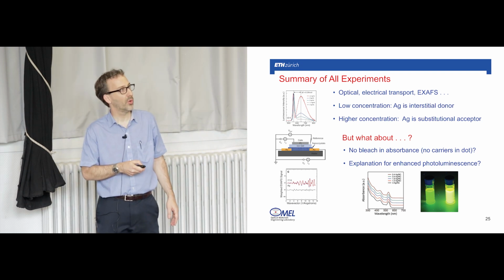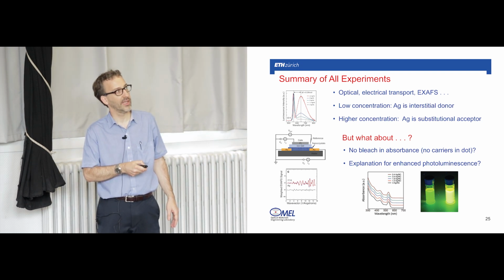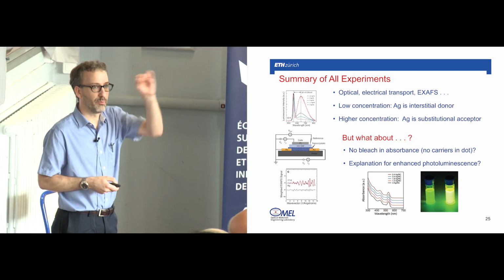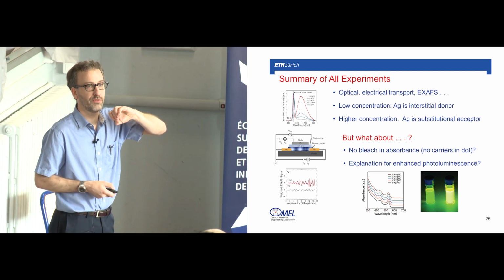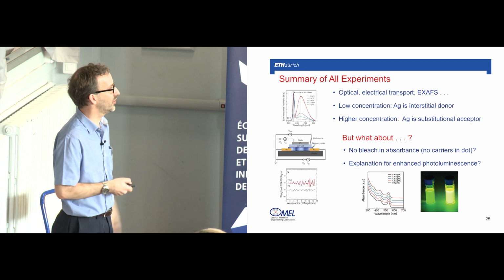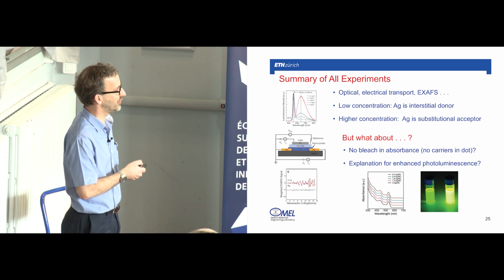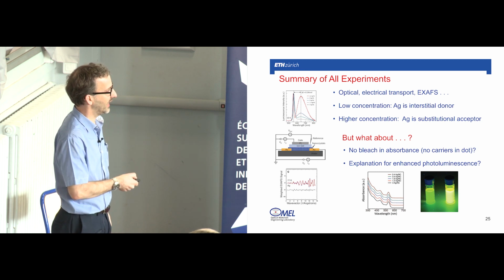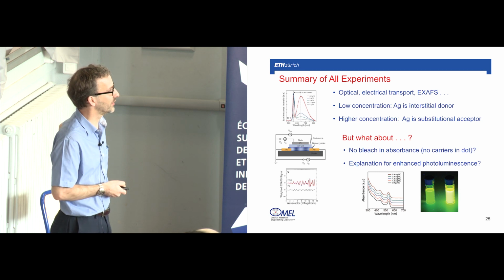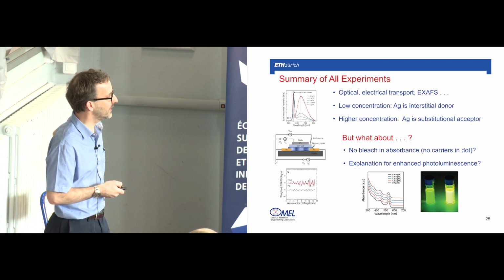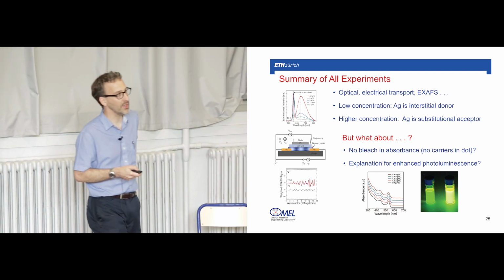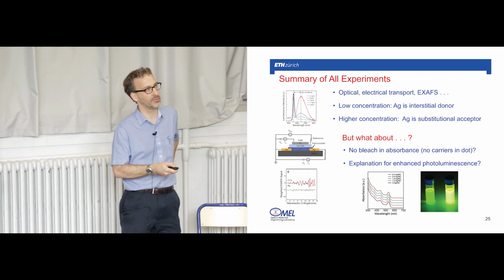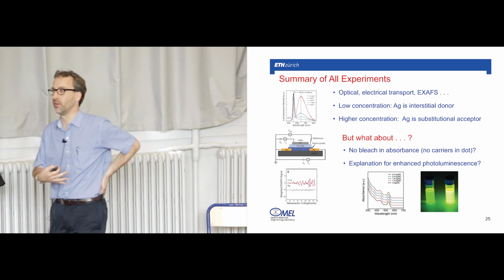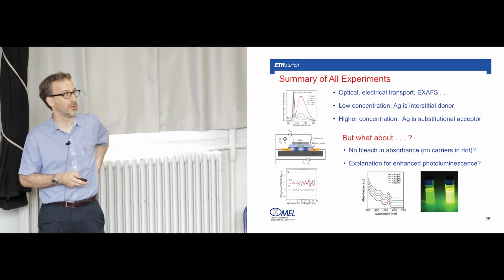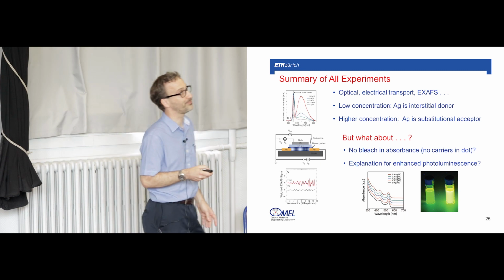So one question is, if we really have electronically active impurities, then if I'm putting carriers into the conduction band, for example, as Philippe just showed us, we should have a bleach in the absorbance. And we don't see any change with increasing silver in terms of the absorbance. So it suggests that there are no free carriers in the dot. And then the other thing we really need an explanation for is why we're getting this very bizarre effect of this big boost in the photoluminescence with just a couple of silver.